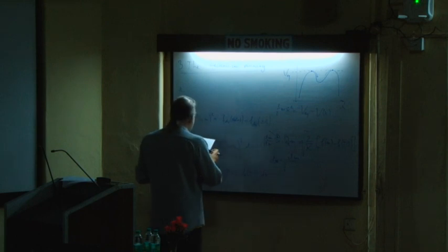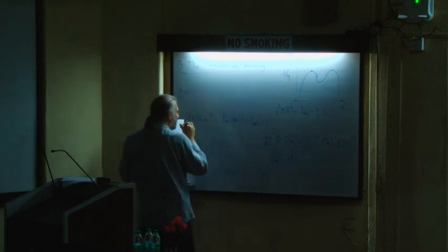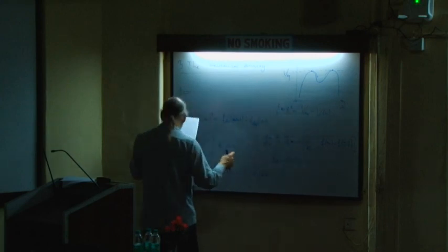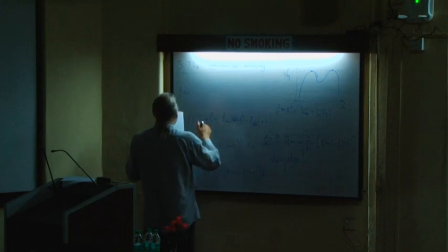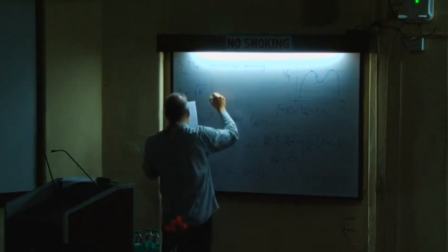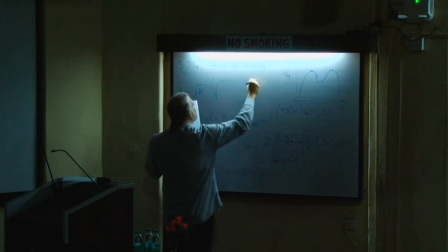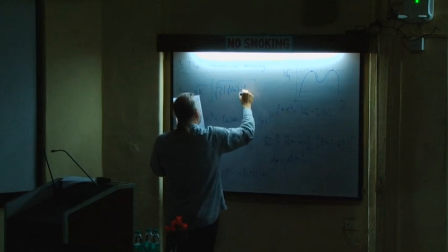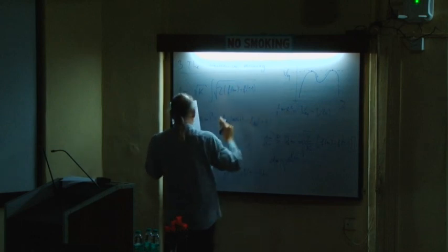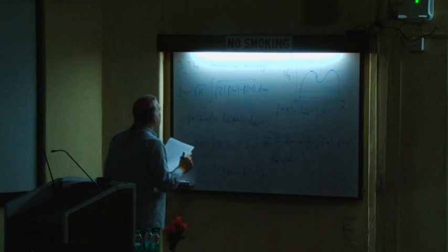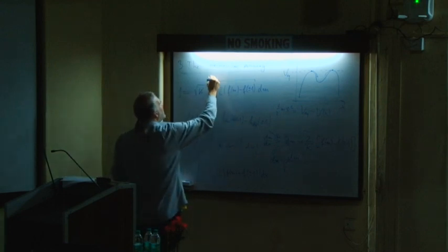Okay. So gamma will be what? I first have to combine the prefactors. I have a 2 here, and then I have a square root of 2 by k. So what I will get is a square root of k here. And then I will get an integral over square root of twice f of m minus f of plus or minus 1. And then I get a dm here. And so here I have to integrate from minus 1 to plus 1.